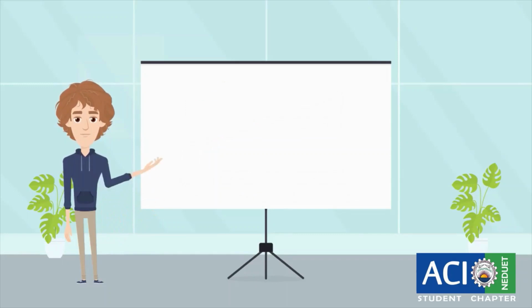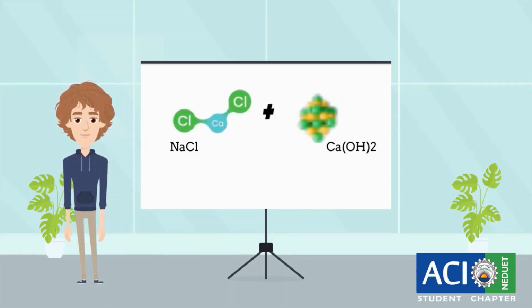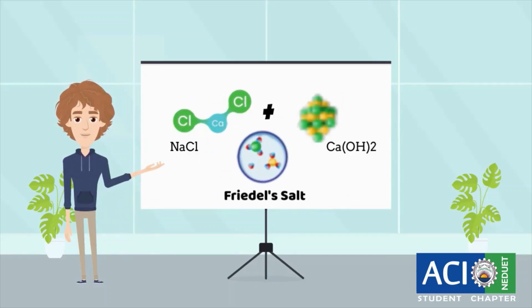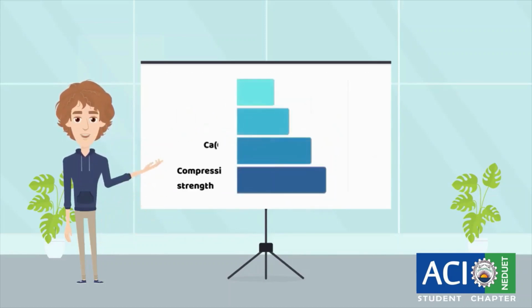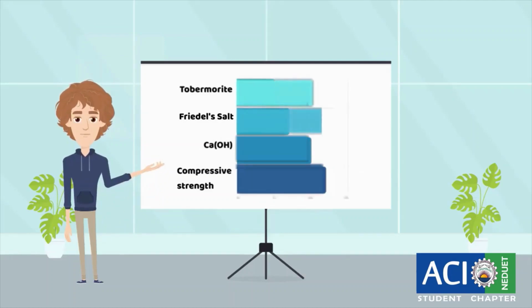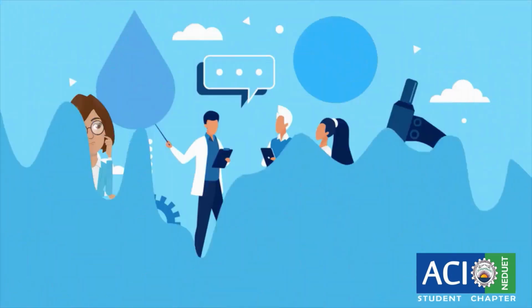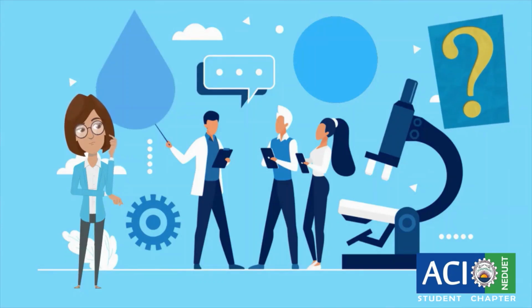Continuous reaction between sodium chloride and calcium hydroxide produces Friedel's salt, which directly fills the pores in the concrete, improving the strength and durability. From the microstructure review, the tobermorite increases up to 7.31%, Friedel's salt up to 7.71%, and calcium hydroxide decreases about 15.82%, which can cause a difference in compressive strength of about 1.93% between a seawater concrete and a freshwater concrete. Rooting for concrete sustainability and resource preservation, it has to be asked how much water can we save by substituting seawater in concrete.